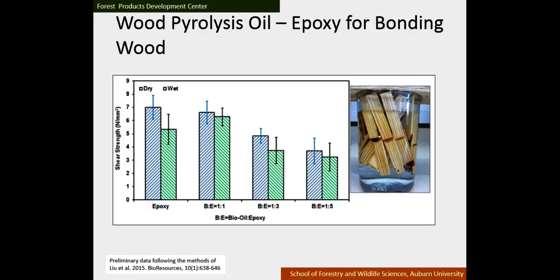to do two things. One, to react with the epoxy, but have a little bit left over to react with the wood substrate. And the reason you want to react with the wood substrate is because the bio oil is hydrophobic. And so if it can tie up sites, through different ways, which is beyond this discussion, it can maybe make the wood more moisture resistant. And so that's what we found, we found that the epoxy could perform well with the bio oil. So what we think is going on is that the bio oil keeps the wood from shrinking and swelling when you dump it into the water, so there's less force on the adhesive bond line. So then it holds together.